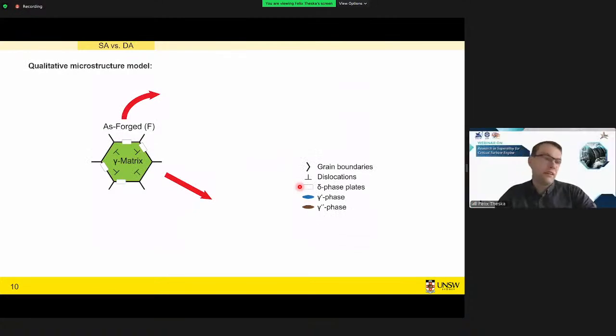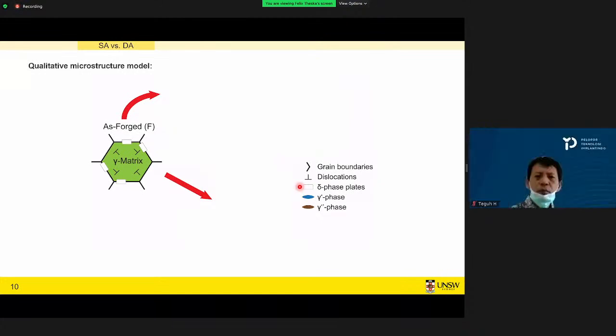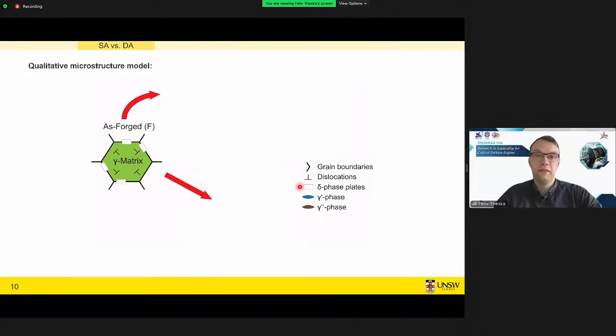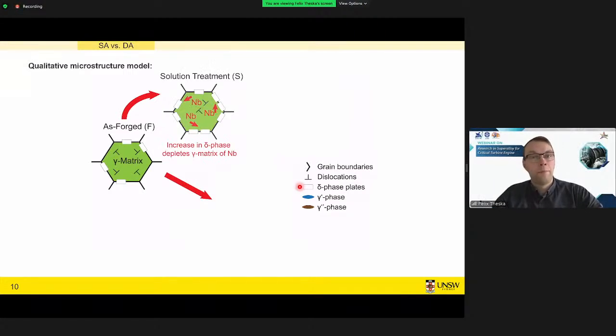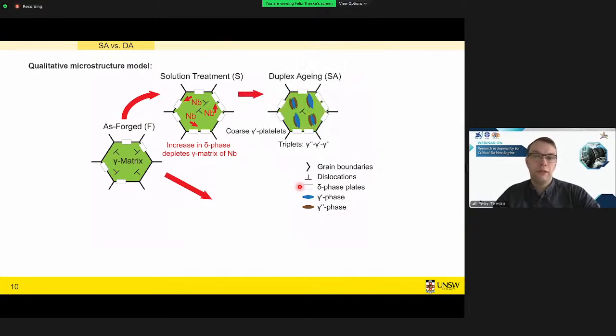Okay, now we already have some insights that this different processing actually changes the structure of these precipitates, and we can summarize what we have found out in this sketch of a microstructural model, where we start in the as-forged condition, where the matrix contains high dislocation density and very little delta phase. If we do a solution treatment to the material, we increase the delta phase, which is rich in niobium. So it takes niobium from the gamma matrix, but we also annihilate some dislocations. And this condition favors the gamma prime precipitation, where we find it as the center particle or the larger particle.